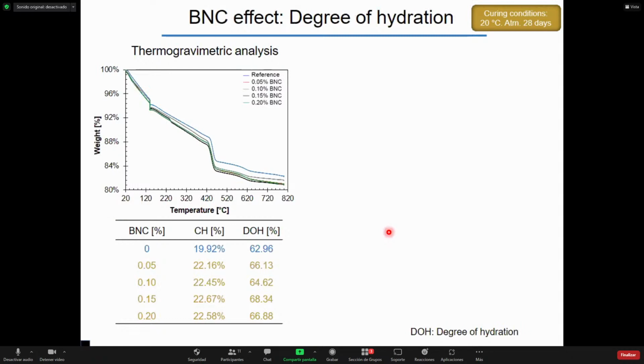To determine the Portlandite content and degree of hydration, we heated the sample. So we can determine the content of Portlandite, for example, by transforming the weight lost at 420 degrees to the real content of Portlandite of the solid phase. We can do the same thing by taking the initial and the final temperature in order to determine the degree of hydration. In this case, we saw that as we increase the bacterial nanocellulose content, the content of Portlandite and degree of hydration increase as well.